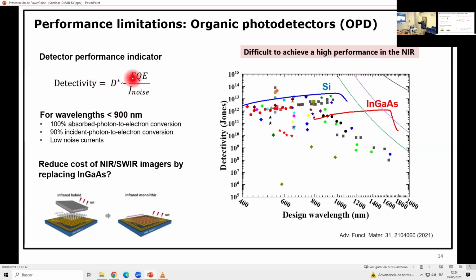And it's proportional to this conversion yield, how many electrons per photon, the external quantum efficiency, divided by the noise current. Proportional to that, there's a proportionality factor. So it's a number because noise is always very low. It's picoamps, femtoamps per square root hertz. So you get a number which is very high and is mainly important on a logarithmic scale. So we are interested in 10 to the 12th, 10 to the 13th, and the unit is Jones.